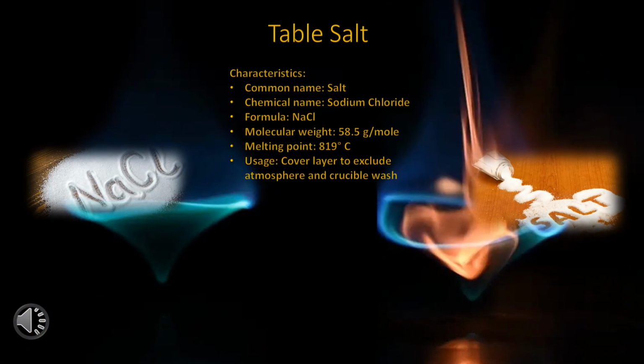Sodium chloride is nothing more than table salt. During fusion it will melt, but will not fuse with the slag. It is used as a cover layer to exclude the atmosphere, thus reducing the oxidation potential of the surrounding air. It also acts as a detergent in some ways, as it washes the sides of the crucible. It inhibits small particles of lead from sticking to the side of the crucible, therefore reducing losses of precious metals. As a top layer, it reduces the risk of boilover due to escaping gases as it floats on top of the slag.